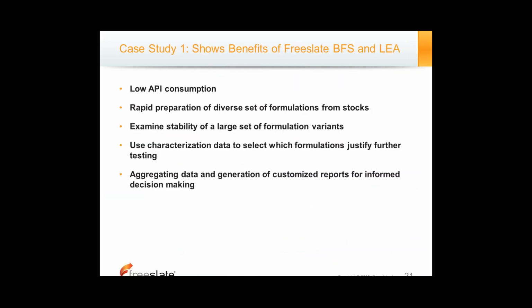So this case study is showing the benefits of what we call the BFS and the LEA software. Using automation and using the system to perform otherwise menial manual tasks, we can have much more efficient workflows, and we can reap many of the benefits. So we can use a small amount of API because the system is set up to make multiple 96-well plates at low volumes, and the same material that we use in one plate, we can subject to three different analytics.